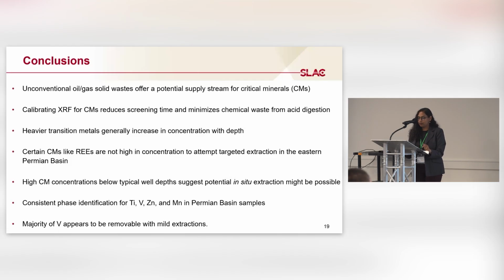Finding high concentrations of certain critical minerals like vanadium could potentially suggest that we could do in situ extractions there. Consistent phases were identified for some elements, and the majority of vanadium seems to be extractable with mild reagents.